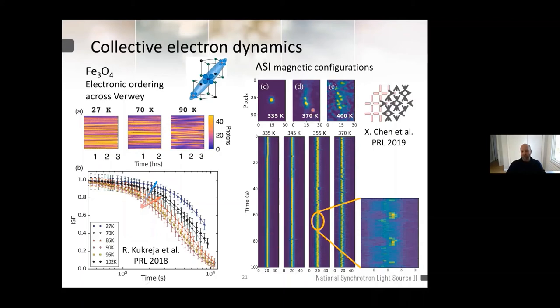If you warm up, these defects also have a dynamic because they bounce back and forth on multiple states, as is very evident in the part that I zoomed in here, where there is a kind of instability between some states. Obviously, this is known from other techniques like PEEM, for example, that can access the direct full-field image over a large area with very high resolution, much higher than what we can do. But when it comes to dynamics, and also correlation between images, it's very difficult to take a very high number of images like this in PEEM and then correlate everything to understand the small details of the movement of the domains.